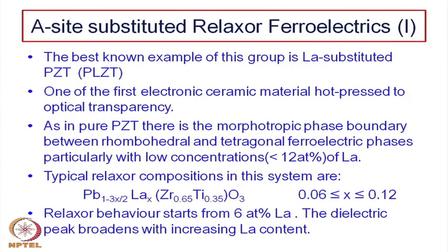Well, that was all about the B site substitution. The other group, as we mentioned earlier, is the A site substituted Relaxor Ferroelectrics, and once again this is based on the most popular piezoelectric material, that is PZT. In fact, PZT has been substituted, where some fraction of lead has been substituted with lanthanum, and of course, this PLZT, lanthanum substituted PZT, has a very important characteristic, and it is one of the first electronic ceramic materials hot pressed to optical transparency. Okay.